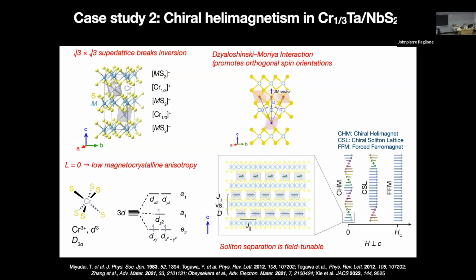What you have when you combine the fact that this material has low magnetocrystalline anisotropy because it's L equals 0, right? So it's this easy plane system, and now you have this DM interaction. What you have in these materials is that in the plane, the moments are all ferromagnetically coupled to each other, but then as you move along the crystallographic z-axis, each layer of these spins is canted a little bit with respect to the one below it, so that you end up with a helimagnetic structure, which you see on the right.